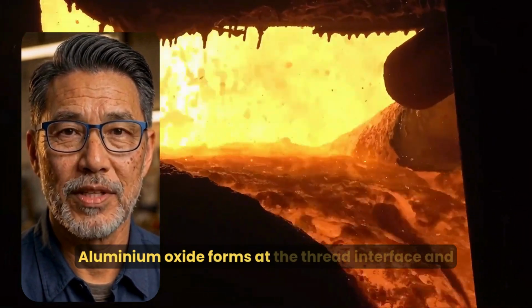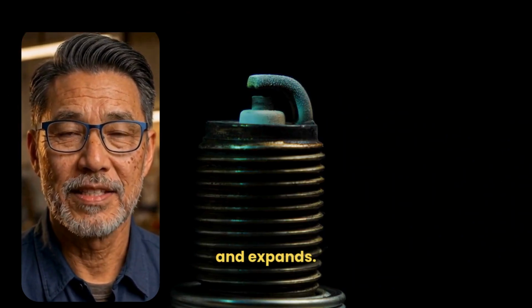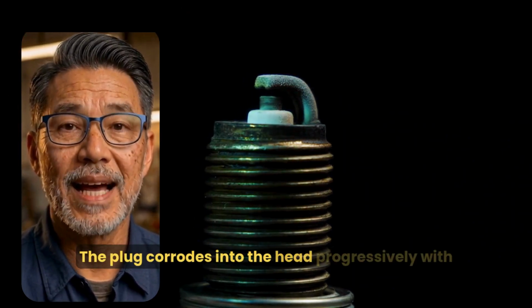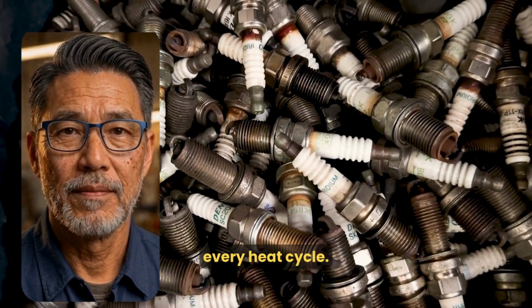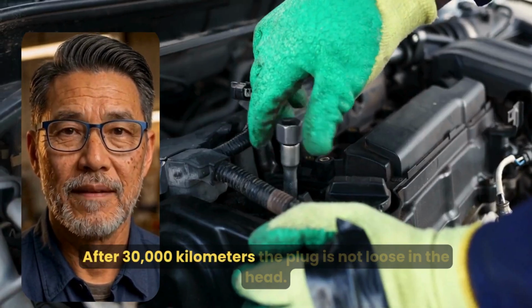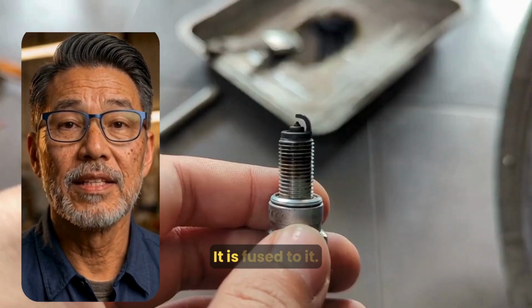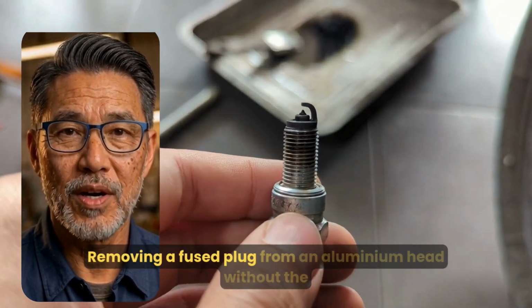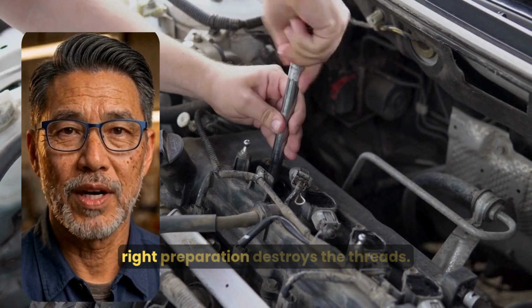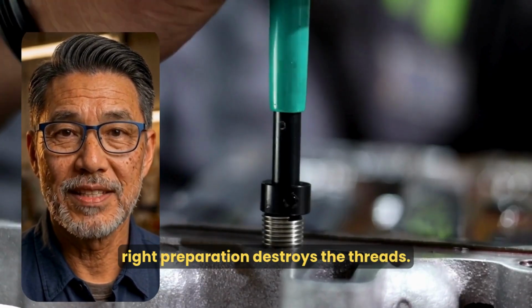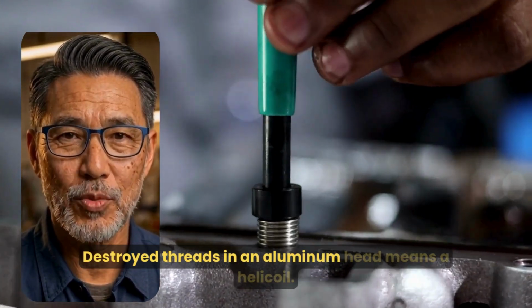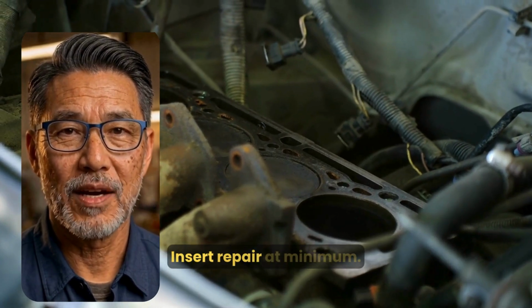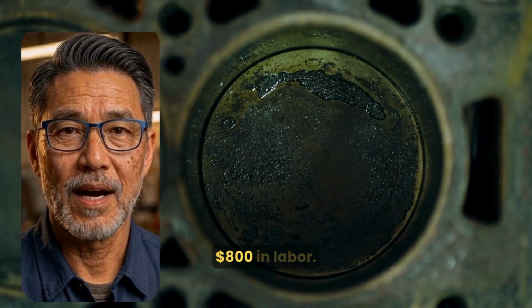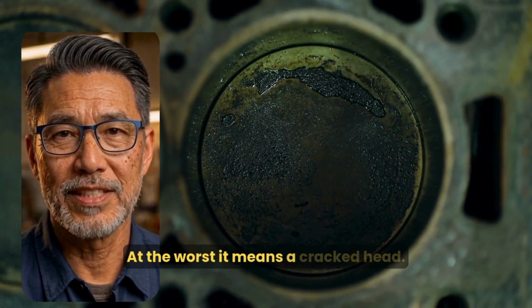Aluminum oxide forms at the thread interface and expands. The plug corrodes into the head progressively with every heat cycle. After 30,000 kilometers, the plug is not loose in the head. It is fused to it. Removing a fused plug from an aluminum head without the right preparation destroys the threads. Destroyed threads in an aluminum head means a helicoil insert repair at minimum. $800 in labour. At worst, it means a cracked head.